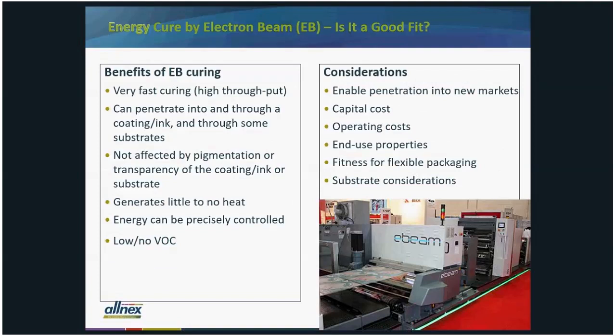So we've talked about some of the benefits of electron beam curing. It's a very fast process. That means high throughput. It can penetrate into and through the coating or ink and through some substrates, meaning it's good for laminating. It's good for curing pigmented systems. You're going to get good through curing, good adhesion. There's not a lot of heat generated, which means that heat-sensitive substrates can be used, which isn't always the case with UV. The energy can be precisely controlled, which means you have a lot of control over the cure of your system, which is always a good thing to have. And again, these systems are generally 100% solids, so they have low to no VOCs.